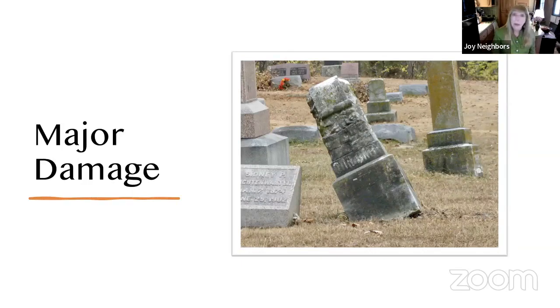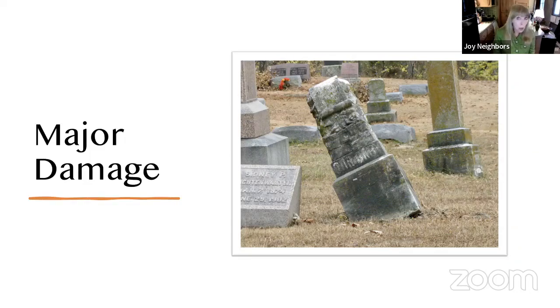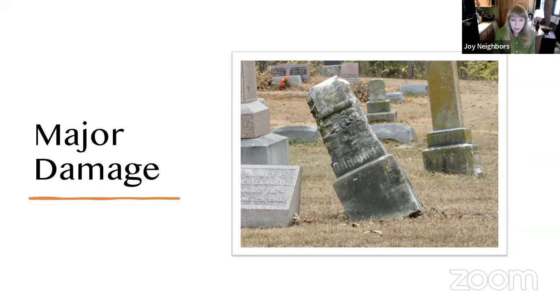Monuments sink depending on their age, weight, type of ground, and whether they had a stable base or were just set flat on dirt. White bronze monuments, made of zinc, are gorgeous and do not deteriorate, but because of their weight they will sink down and at some point will need to be boosted back up and put on a real base. This repair requires placing the base beneath the stone — physically moving it without putting too much force on it and getting it back on that base.